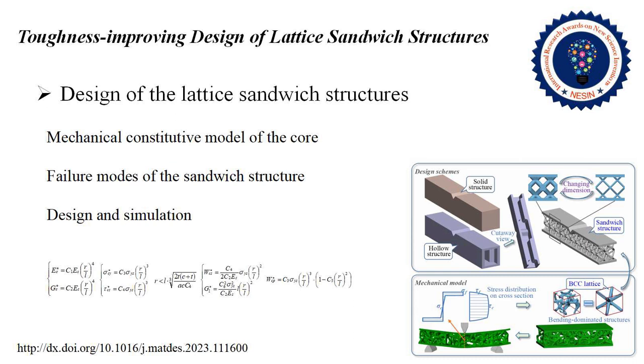And this is the mechanical constitutive model of the core, which is affected by the bending or the plastic hinges of the rods of lattice structures. We can also get the failure modes of the sandwich structure by the equivalent stiffness of the whole structure. Then according to the failure modes, some interesting things can be found. The impact toughness of the lattice sandwich structure is affected by the rod radius of the lattice structure.